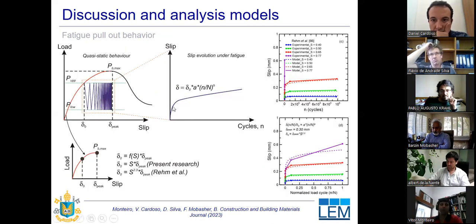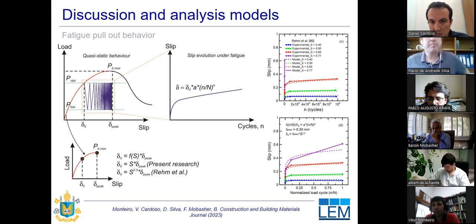The next step is to bring the degradation of the pullout, the bond slip along the fatigue test. So the major way we verified to study the degradation of the pullout is through the slip evolution along the fatigue test. In order to verify the slip evolution, we proposed an empirical equation. A similar equation had already been used in the literature before by Rehm et al. and other authors. They usually used a power law.